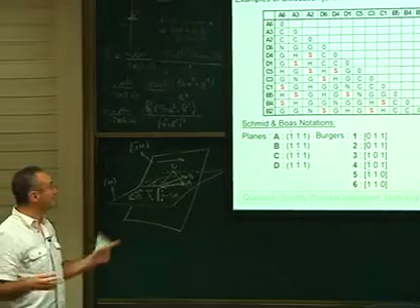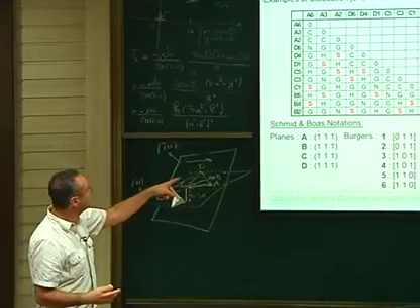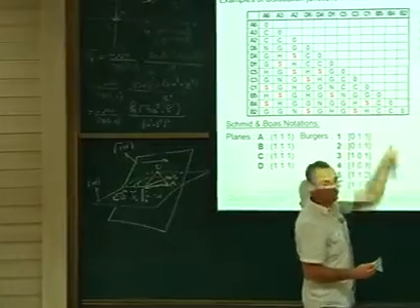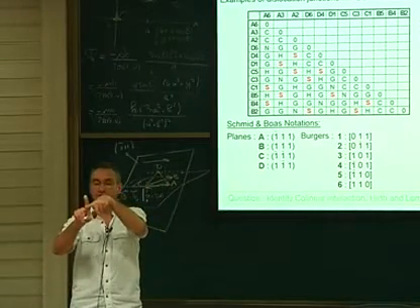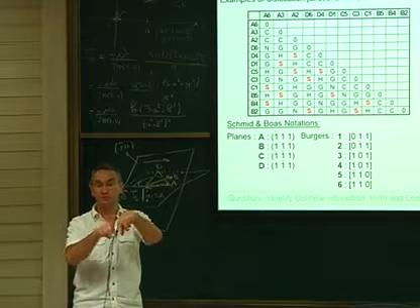You see now, I think we have seen there is one more type, which is the collinear junction. Collinear is here, where you have the same Burgers vector. So in the case where two dislocations meet and they have the same Burgers vector, then the junction has 0 length because you sum up the same Burgers vector, it could give 0.